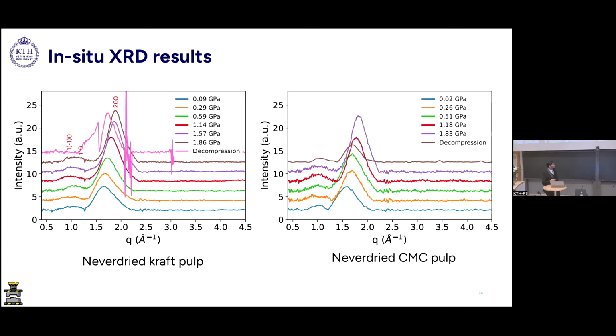And after post-processing the data, we came up with the XRD patterns for both never-dried kraft pulp and never-dried carboxymethylated pulp. In the case of carboxymethylated pulp, we were able to recover a decompression signal. Once we were done with the experiment, we recovered the cell and waited long enough to get the decompression signal. That was basically the signal that we could record. Just from observation, you can see the peaks have a rightward shift. The 200 peak has a rightward shift. The rest of the peaks are not quite clear here visibly, but one peak that you can see quite clearly is this one.